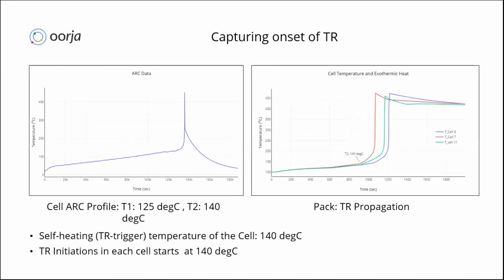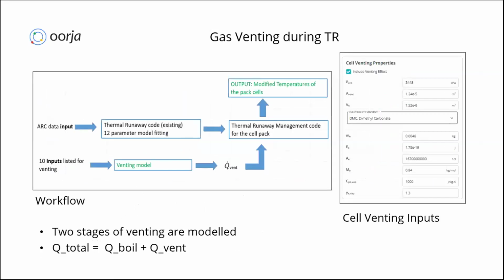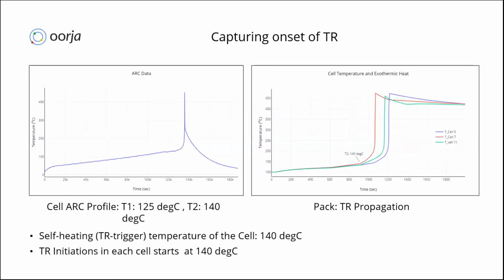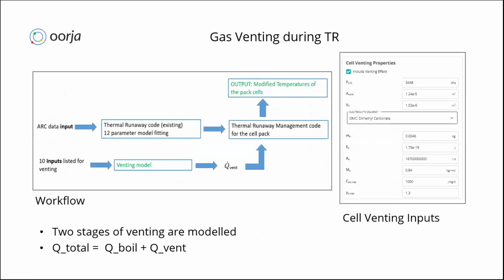So with that, once we start building the model, we can first of all try to understand how well we are capturing the thermal runaway signature of the cell itself, wherein you can see this is the ARC data we have used as an input to the model. In the pack level analysis, we can also get accurate capturing of the onset of the thermal runaway. As and when the cell hits the T2 temperature, the stage 2 reactions also start, and because of that the accelerated heating will start happening inside the cell itself. Not just the onset of thermal runaway and the thermal runaway triggering temperature, we also capture the gas venting during thermal runaway.